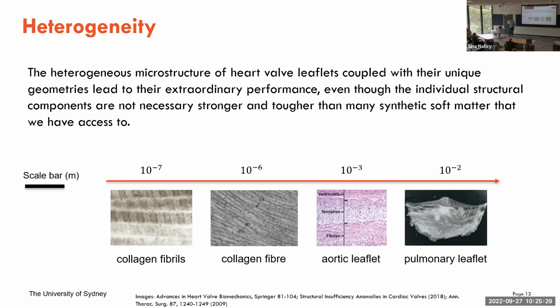Then if you go to the collagen fiber, which is made of these collagen fibrils, we see that they are actually made of oriented collagen fibrils as well. So they are already anisotropic at that level. And then when we go to the next stage, at sub-millimeter, a few hundreds of microns, you would see that the leaflet through its thickness is made of different layers with different compositions.